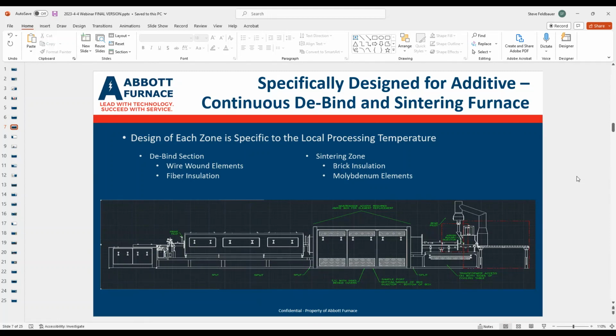And so what's different about this is we don't use this brick and moly construction that's very expensive throughout. If we're going from left to right in our view, you would enter in that section that's a little shorter in height. That's our debind area. In that area, because we're not going as high in temperature, most people are going to be well under 650 degrees C. What that means is we can put in a lower temperature insulation package, as well as use wire wound elements.